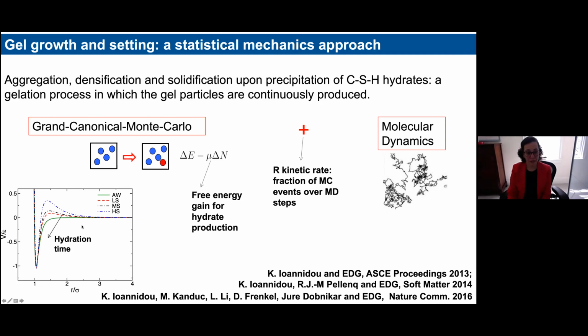We have used this type of scheme considering different types of interaction. These are a simplified version of the profile that I was showing you, in which we studied how the presence of this intermediate range repulsion, which can appear in the very early stages of hydration, and which goes away over time as interactions, as we have seen, become more and more purely cohesive, affects the formation of the gel. Basically, this is the question that we have.